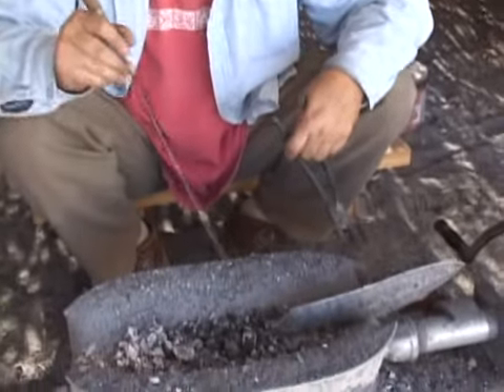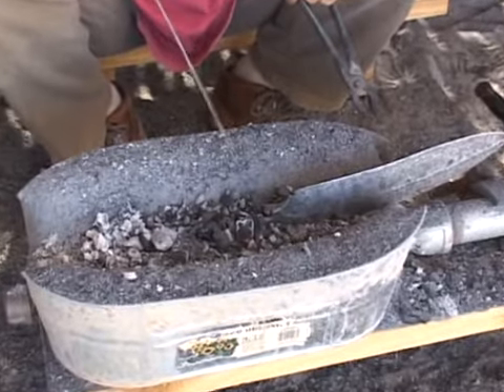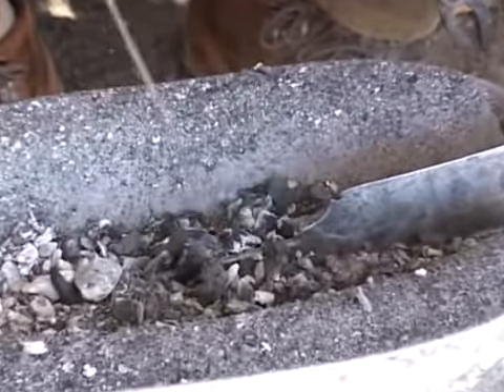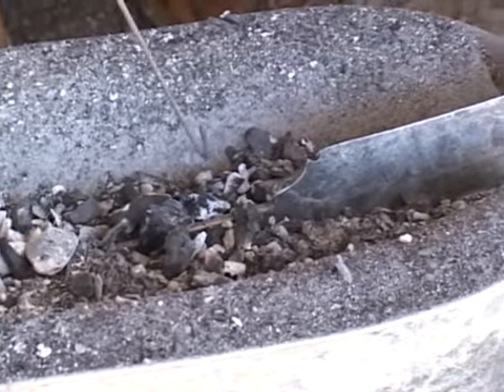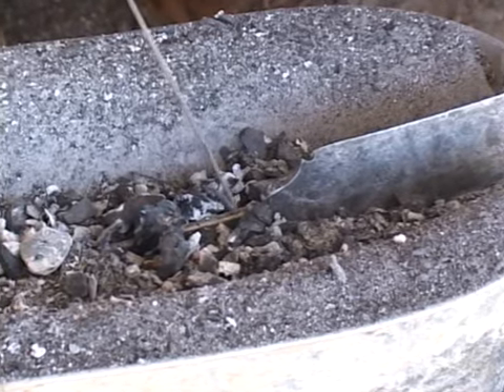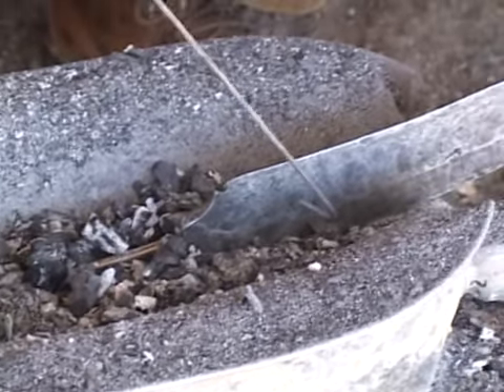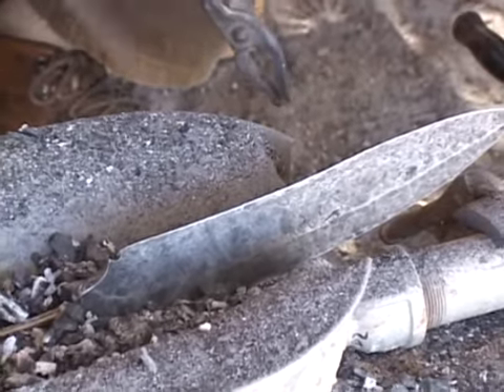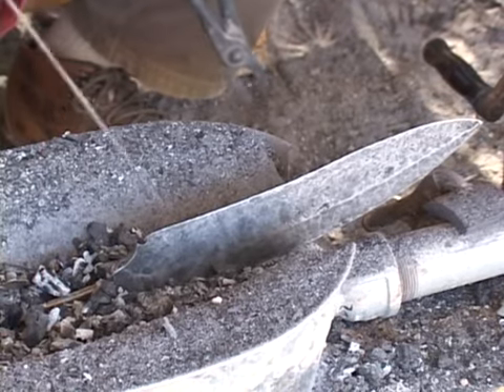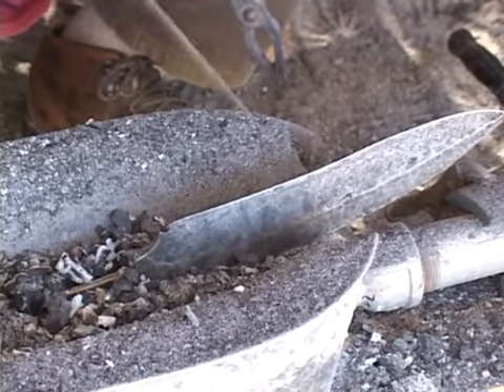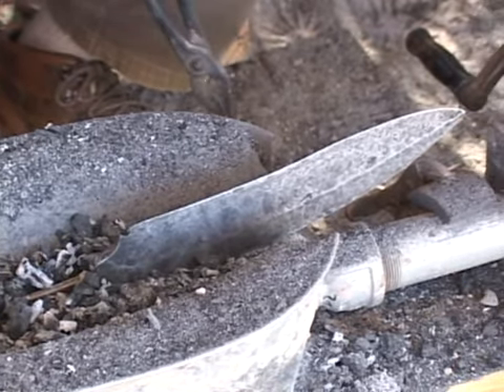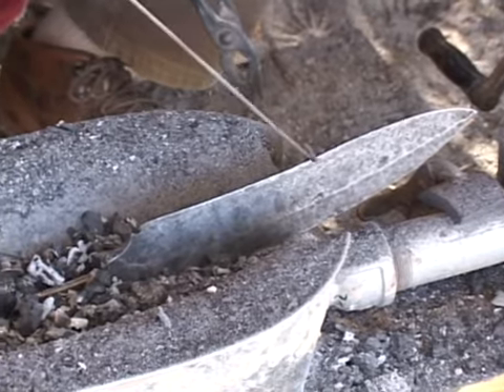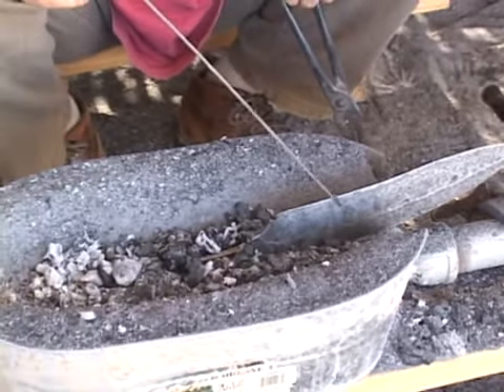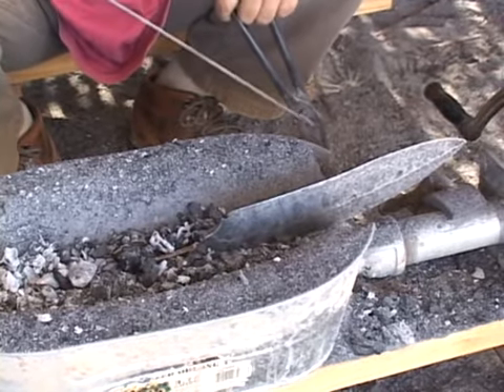Okay, for tempering, we stick it in the hot forge, and I start with the tang. I'm just letting the coals heat up the steel through conduction. I'm going to be tempering it 3 different times. What I want the end result to be is a blue tang, a blue back, and a bronzed edge area. But since I'm tempering 3 times, I temper it until I get a light straw color in the edge. I let it cool to room temperature. Then I go for a dark straw in the edge, and then let it cool to room temperature again. And then I go to a bronze color.